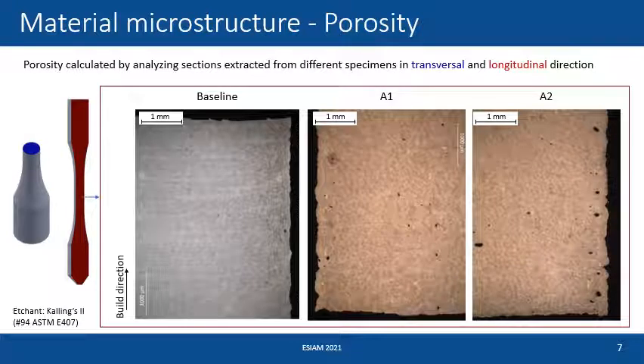Metallographic investigations were carried out to analyze the material porosity, sectioning our specimens in both transversal and longitudinal directions. You can see on the left a picture that shows, with two different colors, the definition of transversal and longitudinal direction. Longitudinal direction is the direction that comprises the build direction, the Z direction.